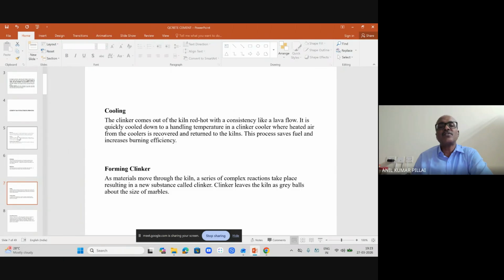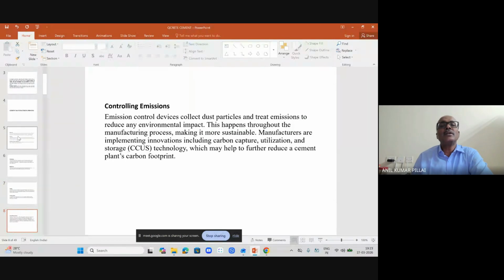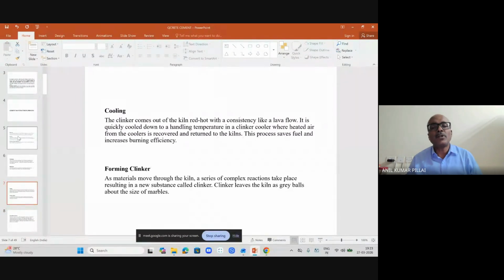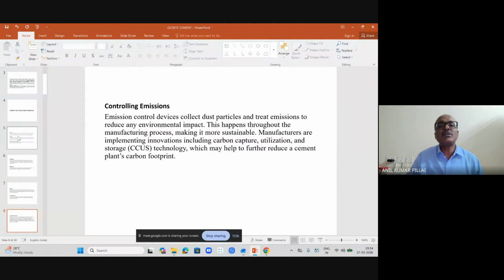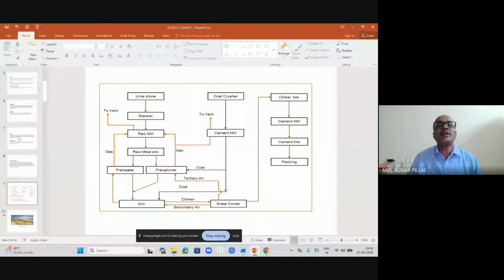And the clinker is formed, which is ground into fine powder and mixed with gypsum. Clinker mixed with gypsum forms ordinary Portland cement. And when you add a blending material like fly ash or slag, you get blended cement like PPC or slag cement. And most importantly, you will find that all-out steps are being taken to control emissions from various steps in the manufacturing process, right from mining till packing. So this is just a brief overview of what is happening.